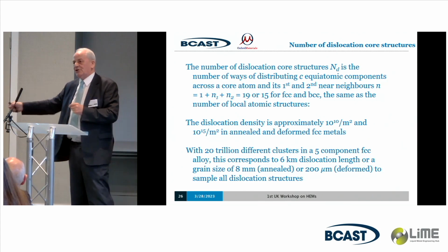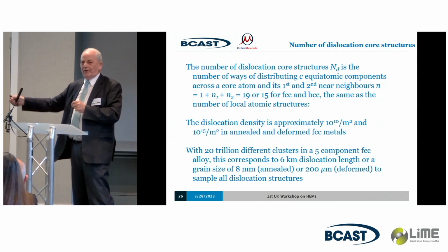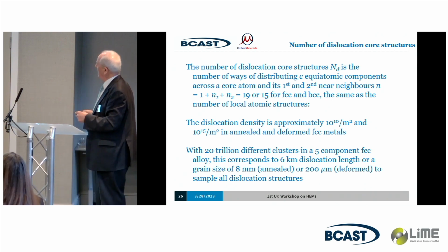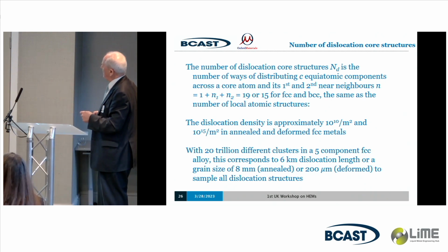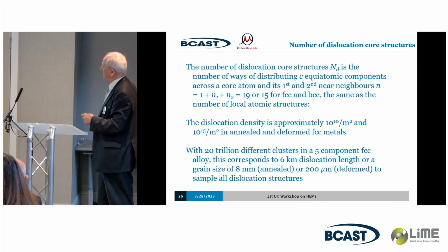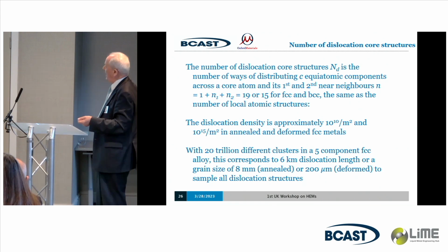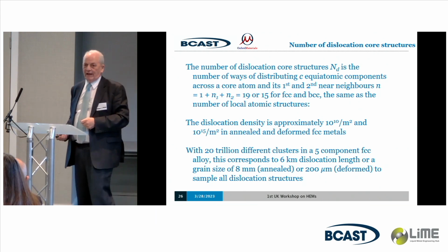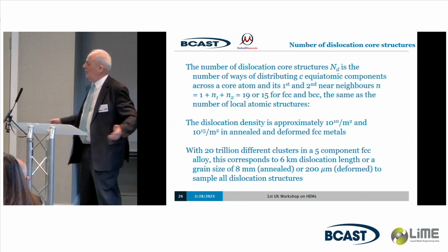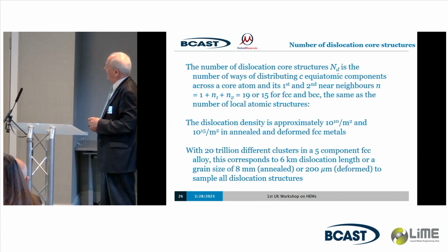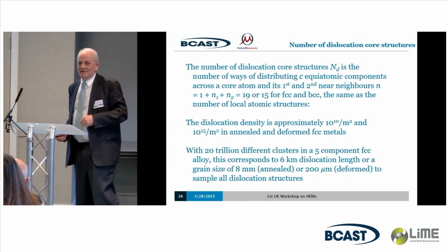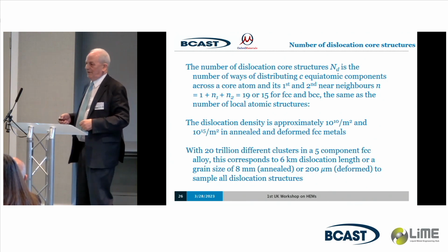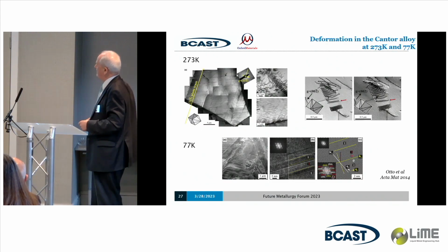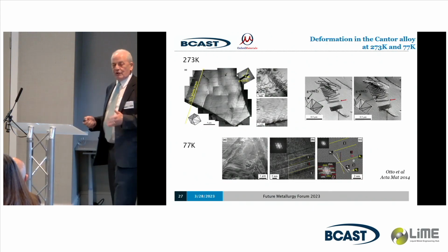Along the core of a dislocation, the structure is varying from point to point. In fact, with a 10 to the 10 per square meter dislocation density in an annealed material, 20 trillion different clusters in a 5-component FCC alloy needs 6 kilometers of dislocation length to sample every possible structure, which with that anneal needs a grain size of 8 millimeters to contain that number of different things in the dislocation. And that's why the strength is so high.